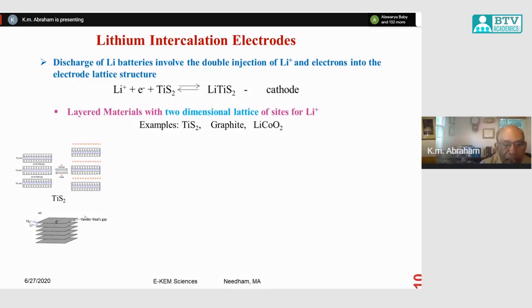So when you discharge your battery, or you insert the lithium into this interlattice spacing, that's what is called an intercalation reaction. You intercalate the lithium ion into that interlattice spacing, and the electrons go into the conduction band in the material lattice structure. So you have really, in this case, a double injection of electrons and ions. And the beauty of this reaction is that it doesn't cause much structural change in the material. The main thing that happens in the crystal lattice of this material is it expands and contracts this interlattice spacing a little bit. That's it. So that's why the reaction is highly reversible. You can insert lithium, extract lithium without too much structural change in the material.